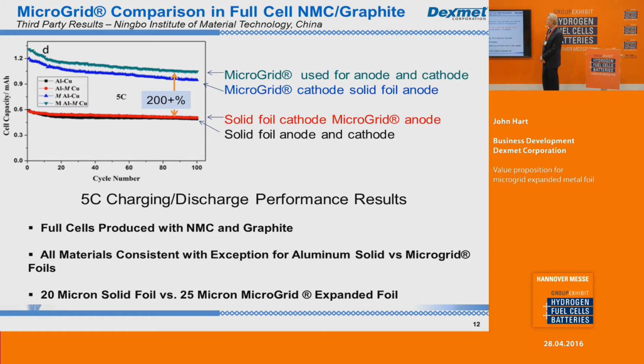These next two slides were part of a paper done by Ningbo Institute in China. They're working with NMC and graphite. The same principle: they took our expanded metal foil and did everything exactly the same in their cell development. This is, again, a caution, a one-layer cell, but it's a pouch cell. They did everything identical on both sides. The only thing they did was exchange the expanded foil for the solid foil. And they did it in four variations: solid-solid, solid-expanded, expanded-solid, and then expanded-expanded.